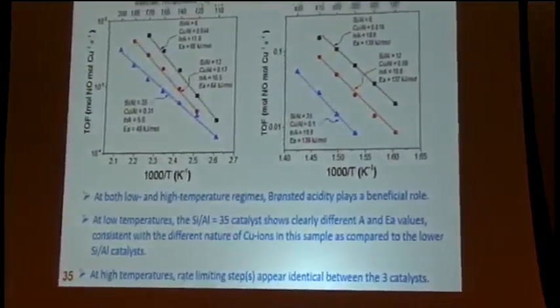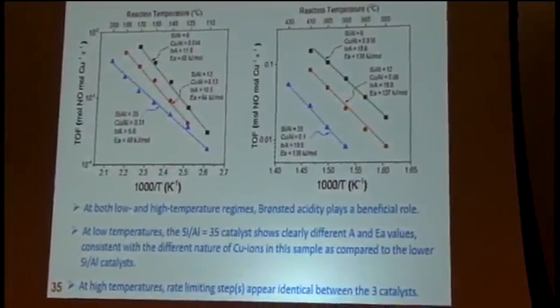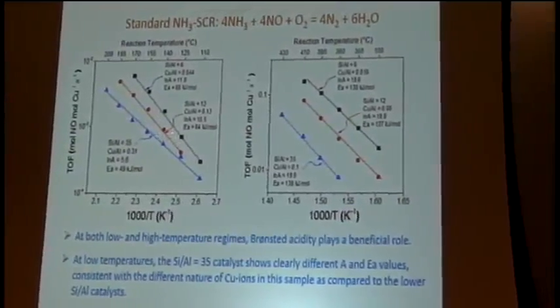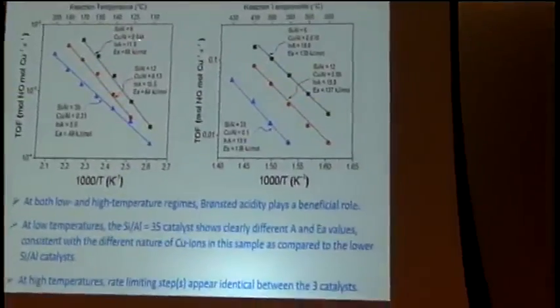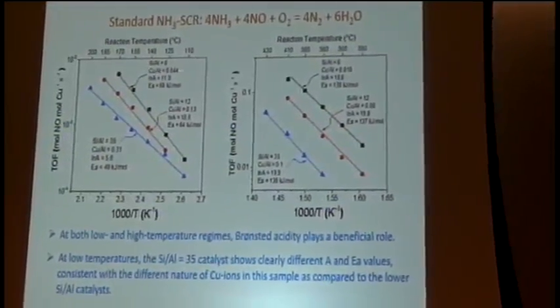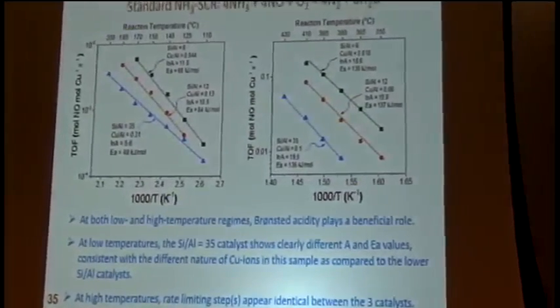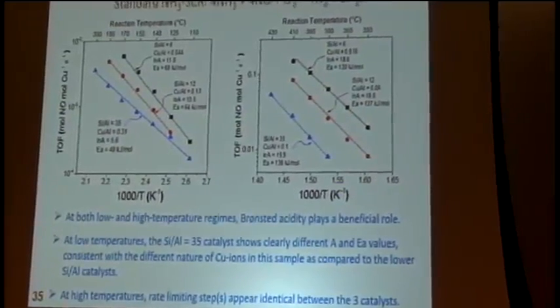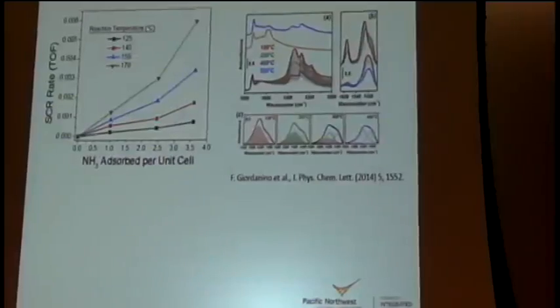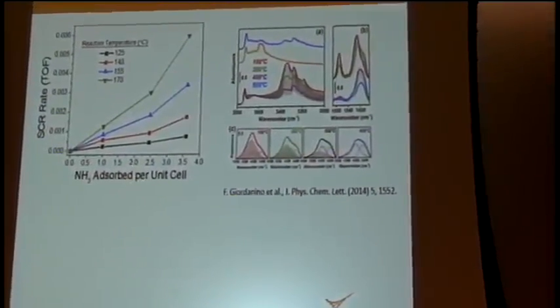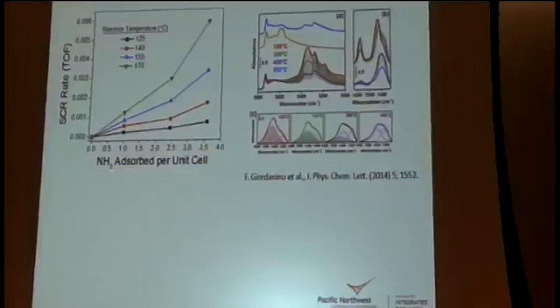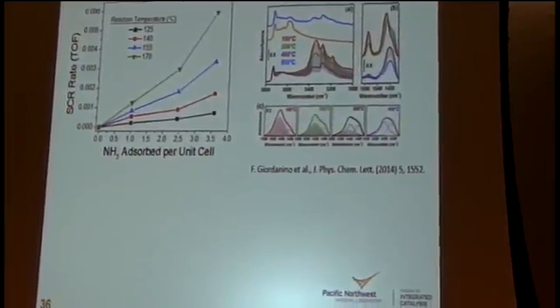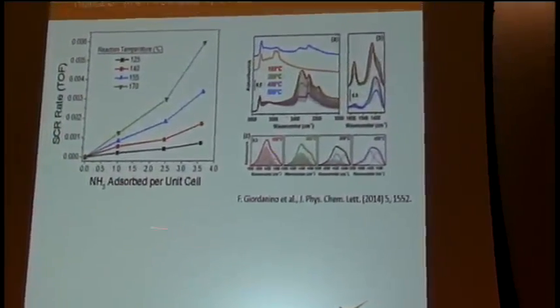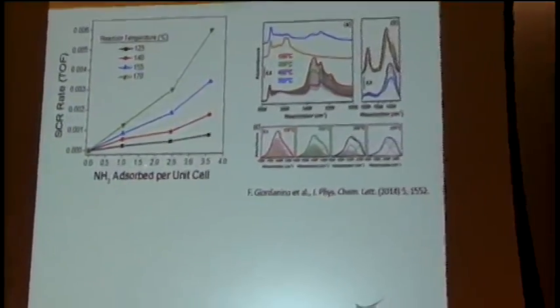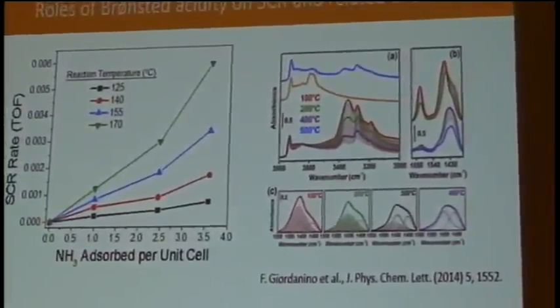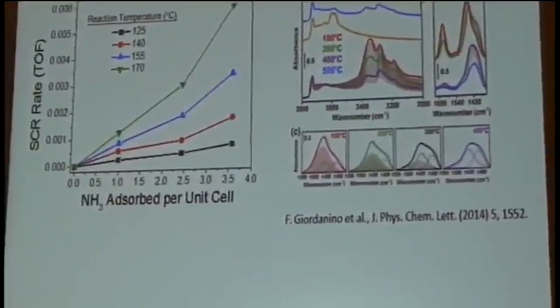And finally, the standard SCR reactions, we also did low and high temperature measurements. In both cases, there is a clear beneficial role identified for Brønsted acid sites. And in both cases, samples with low Si/Al ratios, high Brønsted acid density, show apparently higher turnover frequencies in both regimes. On this slide, we plotted the density of Brønsted acid sites monitored with ammonia TPD and the SCR reaction rates. This shows the low temperature regime, where we have a not bad linear relationship, showing that the density of Brønsted acid sites really benefits SCR reactions at low and even high temperatures.